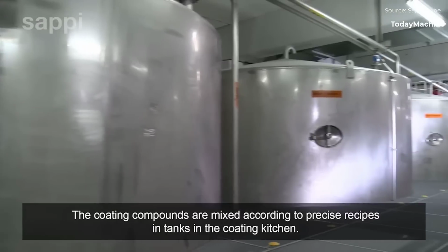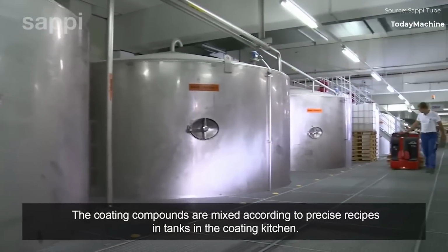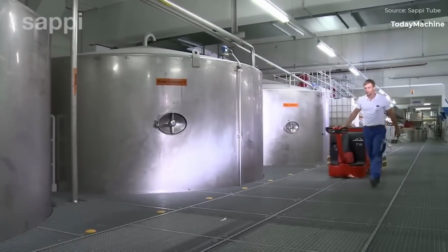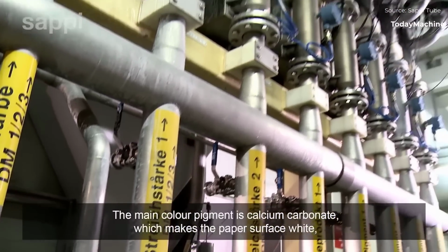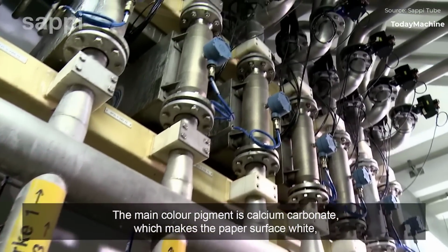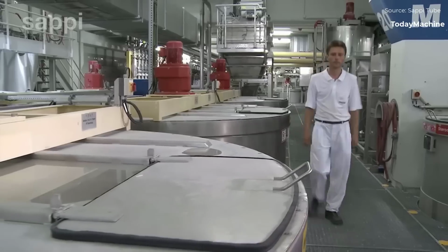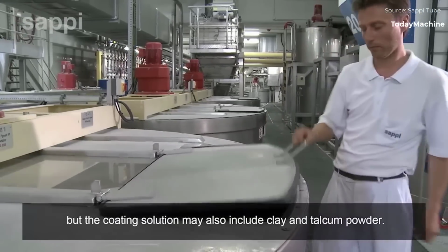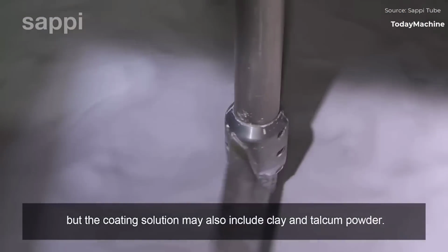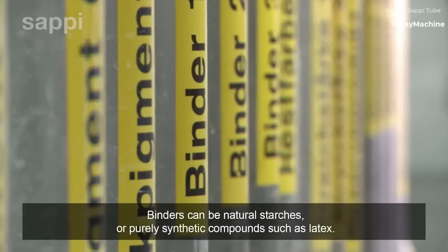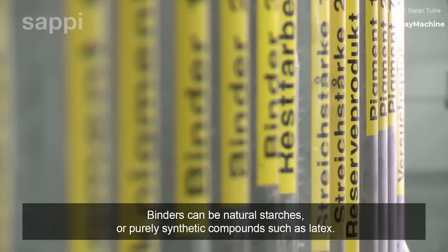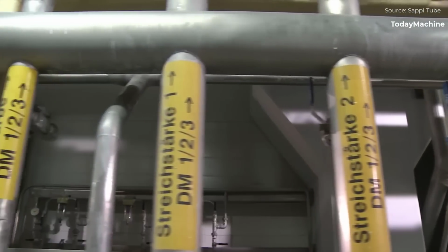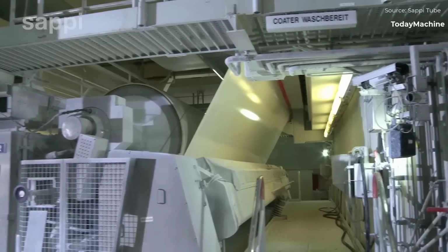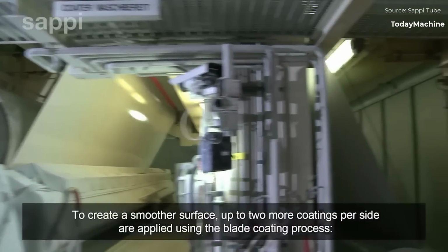The coating compounds are mixed according to precise recipes in specialized tanks within the coating kitchen. The primary color pigment used is calcium carbonate, which imparts a white surface to the paper. However, the coating solution may also include other materials like clay and talcum powder. Binders in the coating can range from natural starches to synthetic compounds, such as latex, which help create a smoother surface.